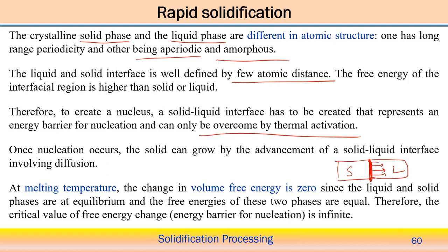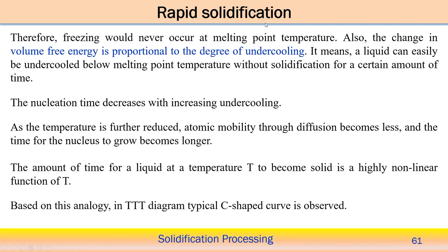the change of the volume free energy between the liquid and the solid phases, when the liquid and solid phases are in equilibrium, is basically 0. Therefore, the critical value of the free energy change is infinite in this case. Because the change of the volume free energy is 0 between the solid and the liquid phase at the melting point temperature, since they are in equilibrium, the critical value of the free energy change, that means the energy barrier for the nucleation, is basically infinite in this particular case.